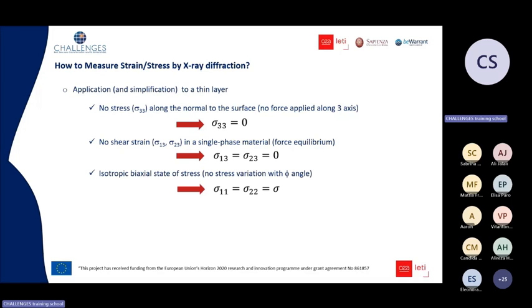And finally, if we have an isotropic state of stress in the plane of the layer, which is a quite common case, it means that sigma 1-1 is equal to sigma 2-2 is equal to one stress value sigma. And from that, it comes that the shear stress sigma 1-2 is equal to zero. So you see, from the six components of stress in case of thin layer, we only have one unknown.